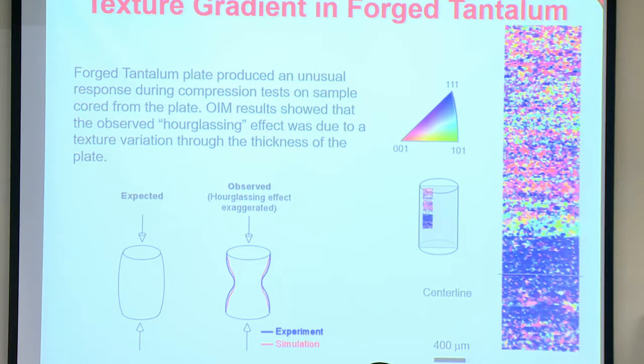This is a tantalum rod cut from a forged plate, and we were interested in the variation in texture because when we compressed it, instead of getting a straight cone or a straight cylinder, we got this hourglass shape where the ends strained faster than the center line, and that is due to a change in orientation. So the blue is material that's in a stiff orientation relative to the compression axes, and the red is in a soft orientation.